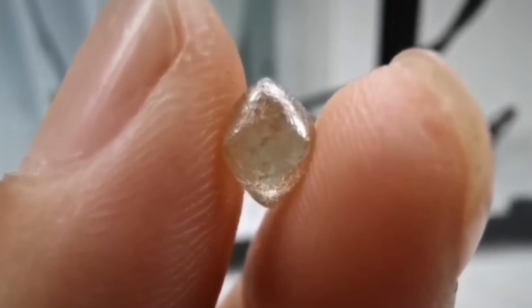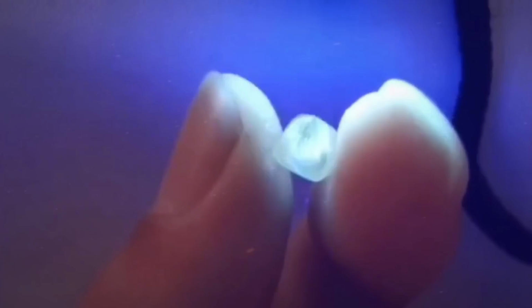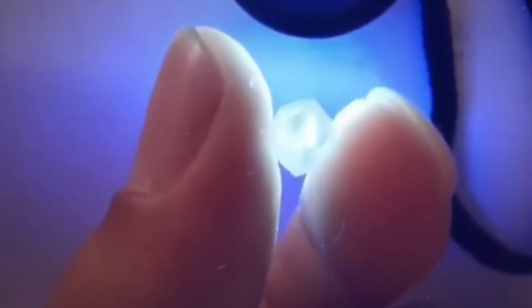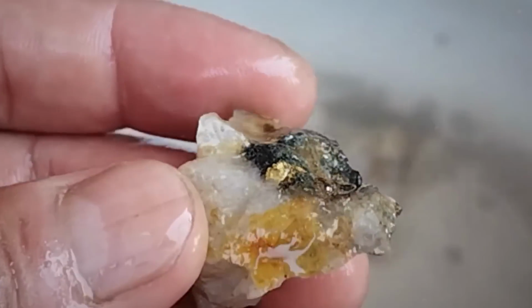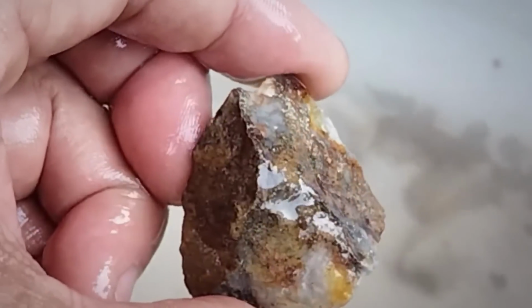A simple setup using a jeweler's scale and water displacement allows you to calculate density with good precision. True diamond will land near 3.52 g/cm³, while most imposters fall short. If a sample passes thermal conductivity, UV profile, and lands within plus or minus 0.03 of the diamond gravity benchmark, you've narrowed the odds of error dramatically.